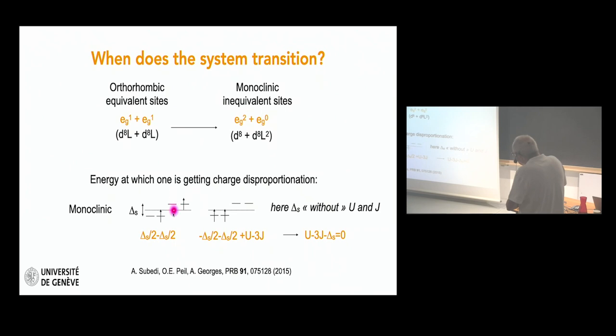You have this change in energy, which is delta S. You have the two sides, and you see that if you put one electron on one side and one electron on the other one, there is no gain in energy, delta S over 2 minus delta S over 2. Now, if you put the two electrons on one side, you gain this delta S over 2, but you pay a price because the electrons are on the same side, and you have the Hund's coupling J. And so this is giving you a condition to switch.